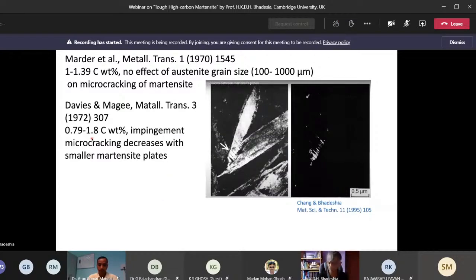Shortly afterwards, there was another paper by Davies and Magee, and they looked at steels with carbon concentration up to 1.8 weight%. Their conclusion was slightly different: if you make the martensite plates smaller in length, then the tendency for cracking decreases. So that's the first clue. I'm not explaining how to do that, but supposing you could, that would make the plates less susceptible to cracking. And it's really interesting, they also identified a role of crystallography.